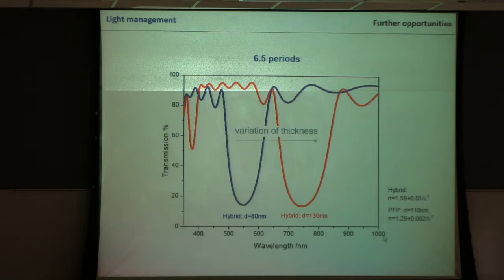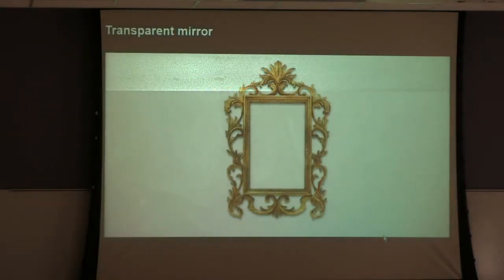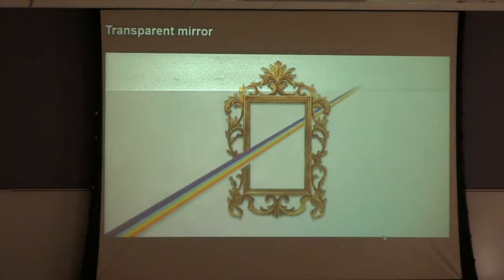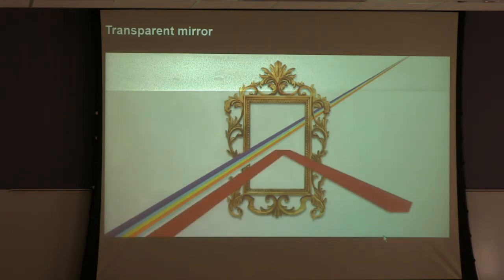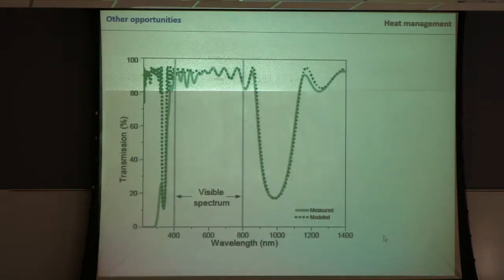Why? Especially inorganic solar cells suffer when they heat up. So paradoxically, when the sun shines on solar cells, they heat up, and their efficiency goes down. So we prepared mirrors that are transparent in the visible, but they reflect the heat, so the near-infrared regime. So here is one spectrum. Nowadays we do much better. It's just actually increasing the layers.